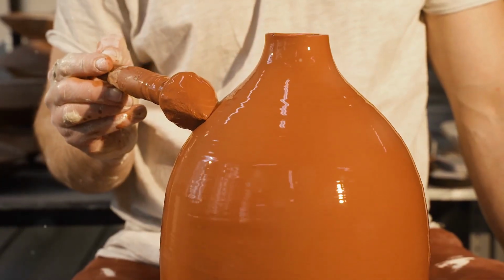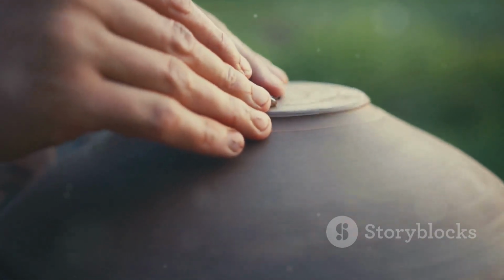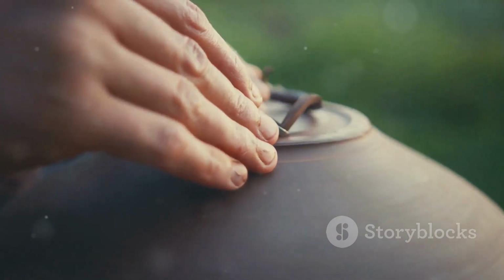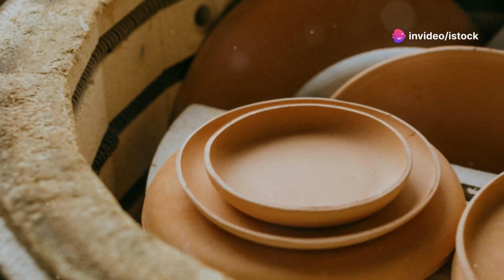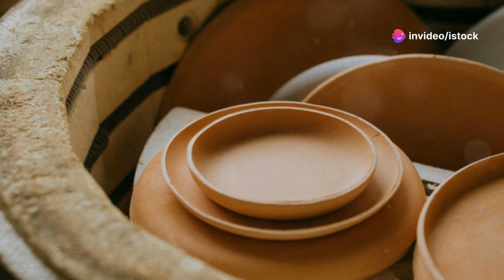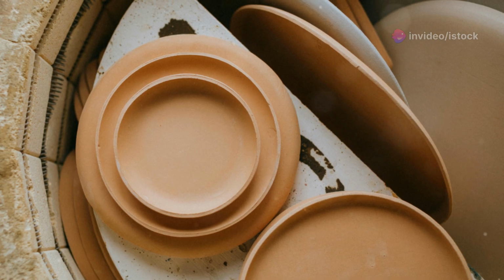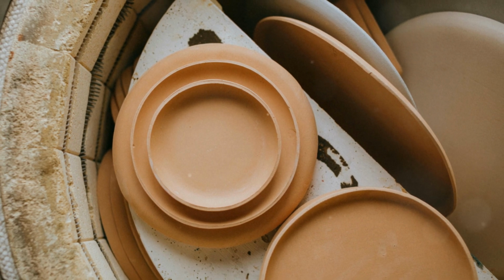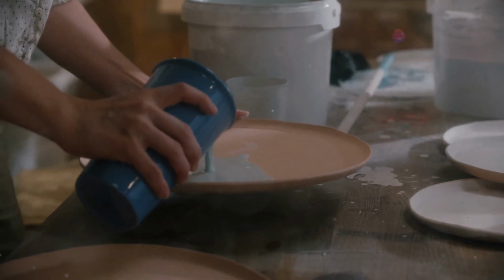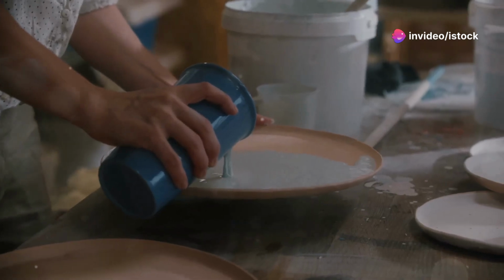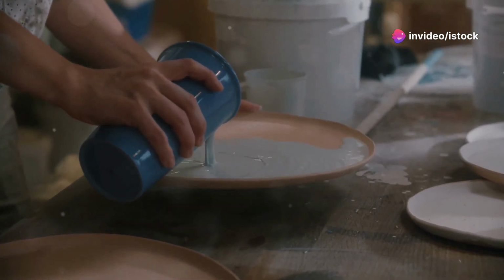When glazing, leave the bottom unglazed. This is important because the glaze can melt and fuse to the kiln shelf during firing, ruining both your pottery and the kiln shelf. This is where the pottery sits in the kiln. The unglazed bottom ensures that your piece can be easily removed after firing without sticking to the shelf. If the glaze touches the kiln shelf, it will stick. This can cause significant damage to both your pottery and the kiln, making it essential to keep the bottom free of glaze. You can use wax to protect the bottom.